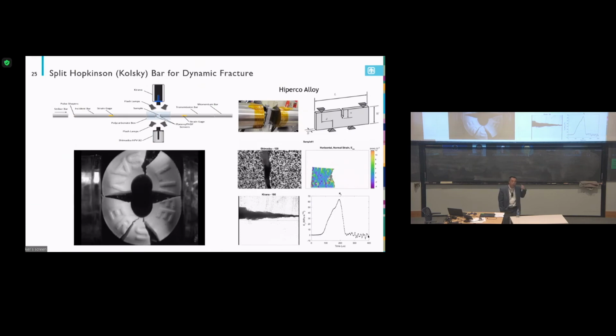But this is mode 1. How do we do mode 2? Mode 2, yeah, we basically just use 4-point bending. We make the pre-crack like this. Then when it's subject to 4-point bending, there's shear over there in the middle, then the crack will propagate. So that's how we do mode 2 fracture toughness. But usually we apply this technique, mode 2 toughness, to composites in most cases.